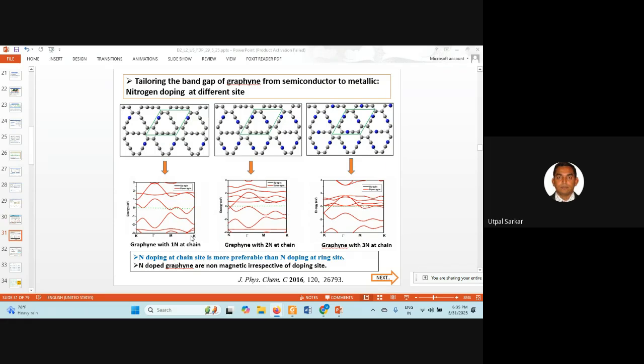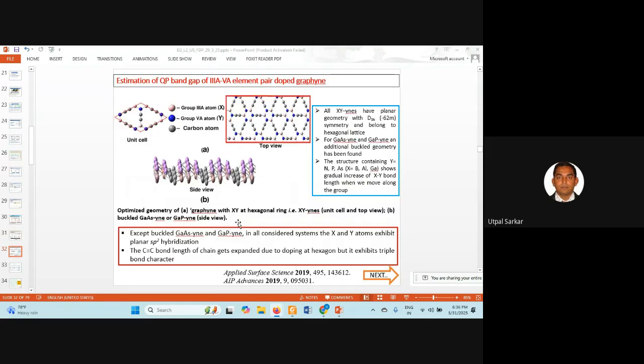Similarly, nitrogen doping at chain site we have done. Okay, so graphyne with one nitrogen doping, you see these valence and conduction bands are now coming down here in all these cases. Okay, so nitrogen doping at chain site is more preferable than nitrogen doping at ring site. This is coming from the stability analysis or cohesive energy, and nitrogen doped graphyne is non-magnetic irrespective of the doping site. Now, some other structures, XY-ynes, we have considered, where X represents boron, aluminium, and gallium.